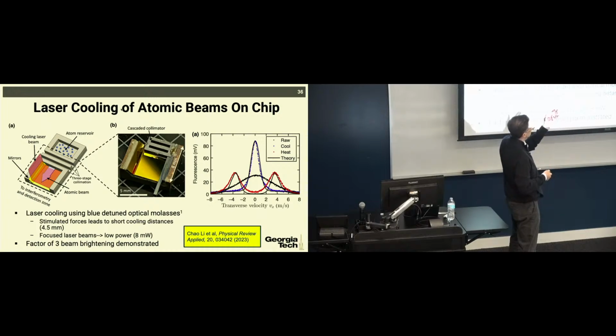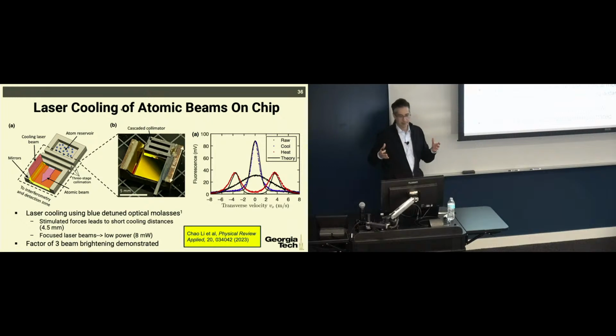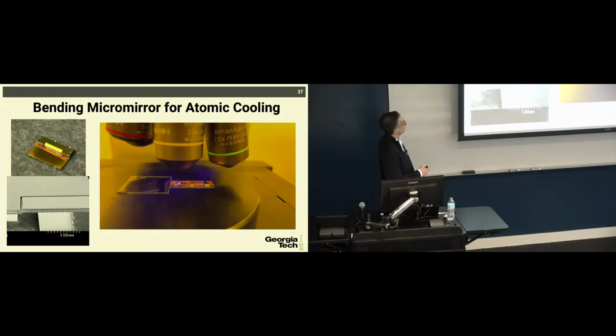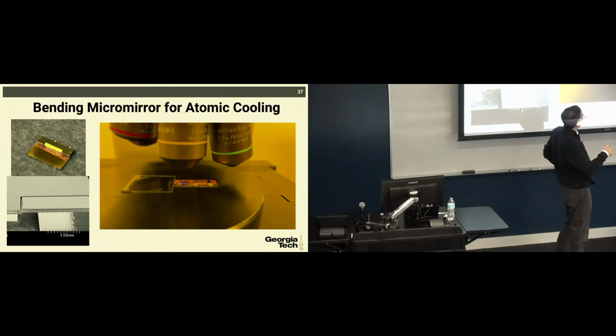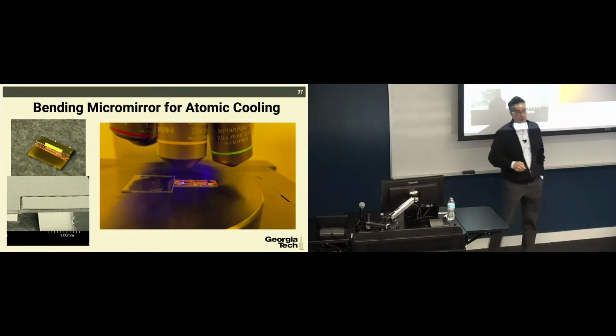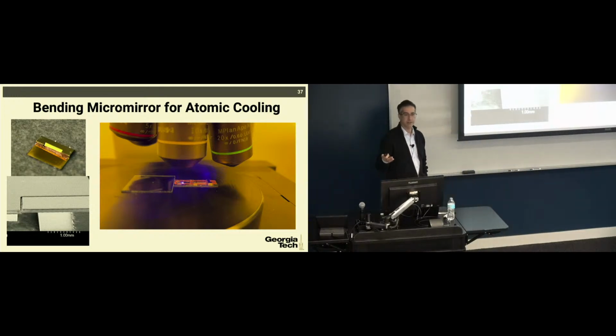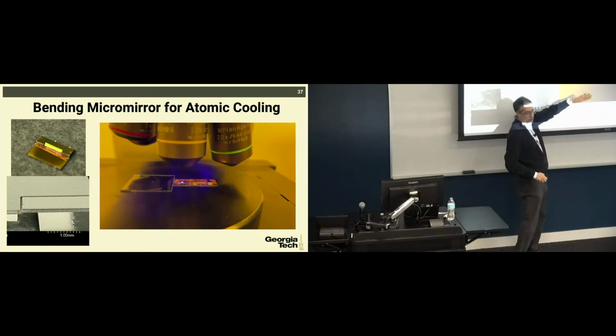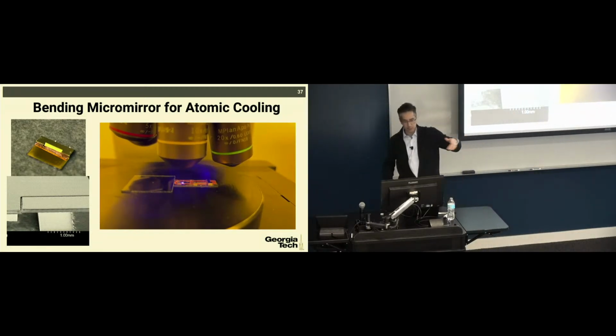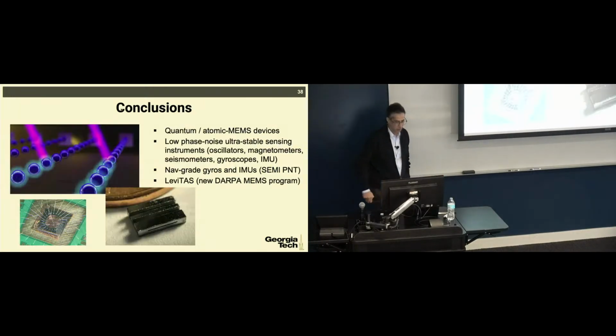after the laser cooling, which is again the first of its type shown in this work as a fully integrated solution. Now you may say that this is not fully integrated because that KOH etched surface didn't work, and now we're working on creating planar mirrors that can then be bent down to any degree that you want, to create these 45-degree mirrors. This is one example of how these mirrors are going to look. You see how bright this is. This is exactly similar to what a macro scale mirror quality would be for deflecting light from one direction to the other. Just take a look at this. This is the mirror being actuated. So on demand, you can actuate it down and it will cause the light to be deflected. Okay, so conclusions.